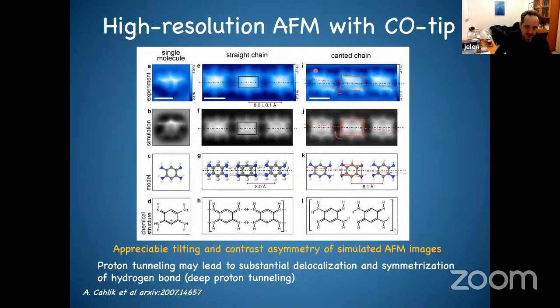So I told you about these chains which are unstable. You see that when we do this high resolution imaging, they are not exactly straight as we see for those guys. They are flipped a little bit. When we do the calculation, this is the DFT optimized structure, and when we calculate the image it is a perfect match with what we have here. And when we introduce this proton tunneling, you see that everything becomes symmetric. So what we claim here is that when you switch on this proton tunneling, this concerted motion, these protons start to jump, or I mean, it's a naive classical picture, but these protons now behave as a wave function. And so they move in a concerted way. So now everything is more stable, and probably you gain some cohesive energy by this concerted motion of protons.